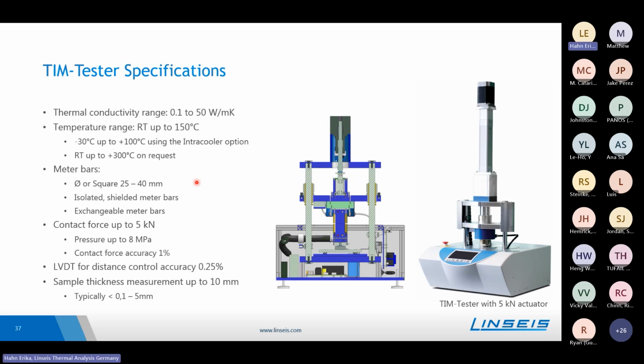The contact force can also be changed. So mainly we use the 1 kilonewton actuator. The pressure onto the material will be realized then according to which geometry the meter bar has. And the contact force can be extended up to 5 kilonewton. You can see here on the right the picture of this customized instrument with a 5 kilonewton actuator so that it will look a little bit different to the standard setup. Mainly the samples are constructed in such a way that the thicknesses are between 0.1 to 5 millimeter. In general, the system can measure samples up to 10 millimeter.